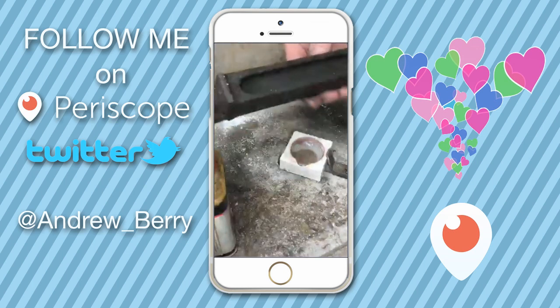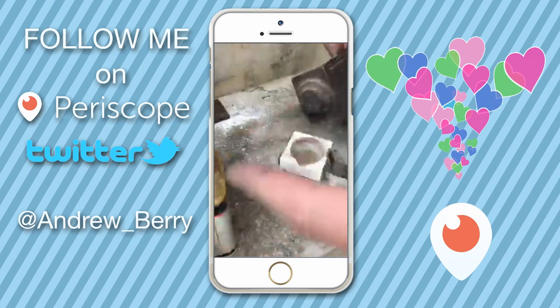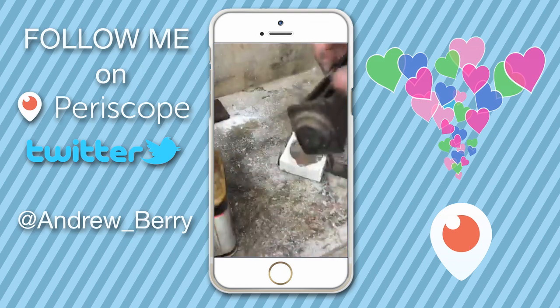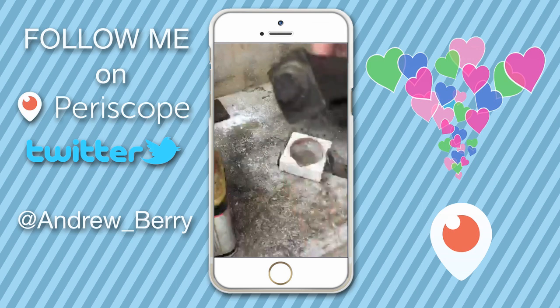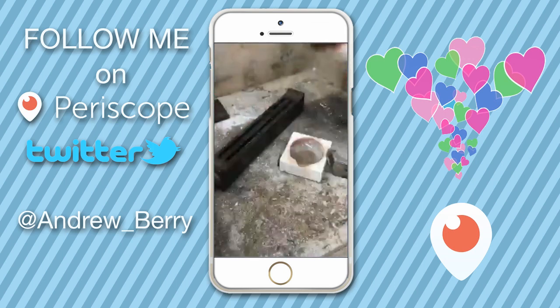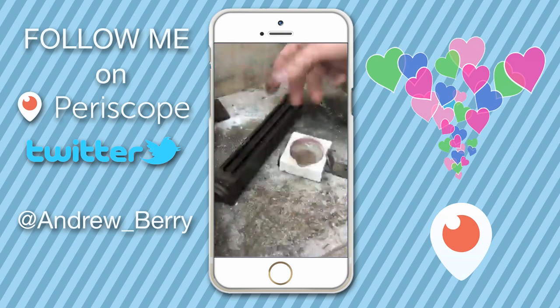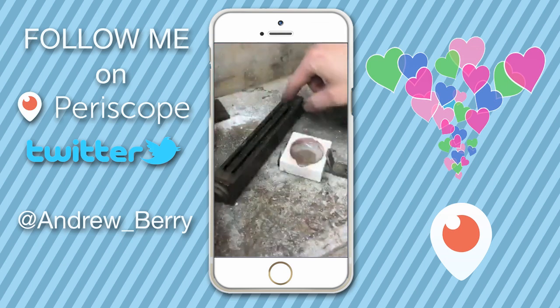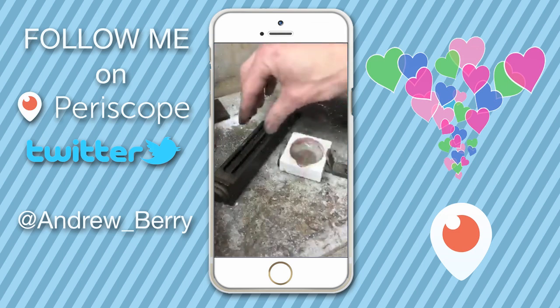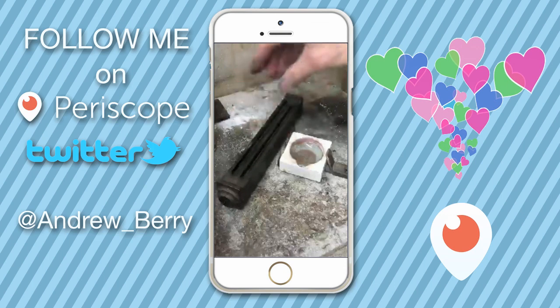So this is the ingot mould that we use. It's normally got a handle sticking out of here, but sometimes I've tapped it on the ground to get the ingot out, and the handle snapped off. It's black because I use some 3-in-1 oil. It's always nice to put a little bit of 3-in-1 oil into the channels. It coats them with oil, and when the oil burns, it produces a nice carbon finish on the ingot mould. This is really important if you've got a new ingot mould and there's paint on it.